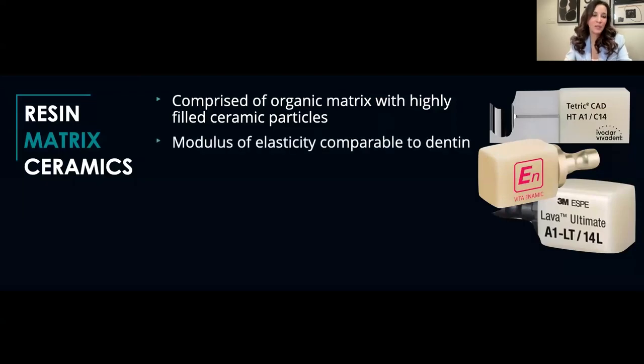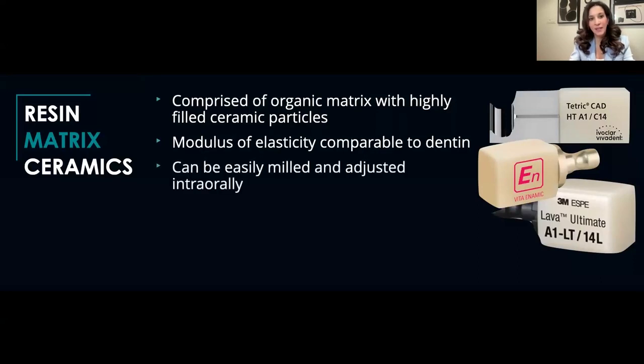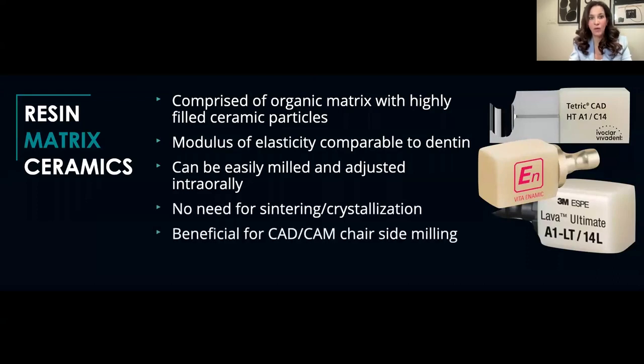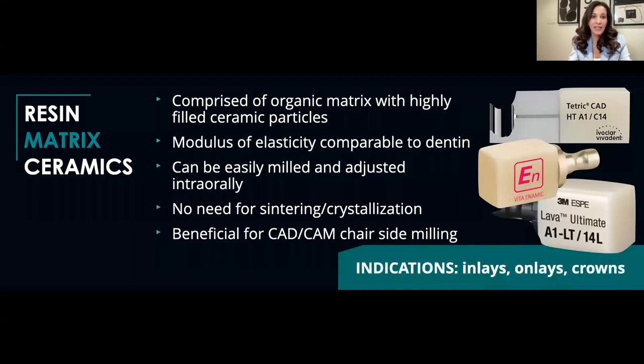But the nice thing about it is the modulus of elasticity is comparable to dentin. And it can be very easily milled and adjusted intraorally without the need for sintering or crystallization. So that's a real draw for anyone who's doing chairside milling, where you don't need to spend the extra time to either sinter or crystallize as you would for zirconia or particle-filled glass. And the indications for this material are for inlays or onlays or crowns.